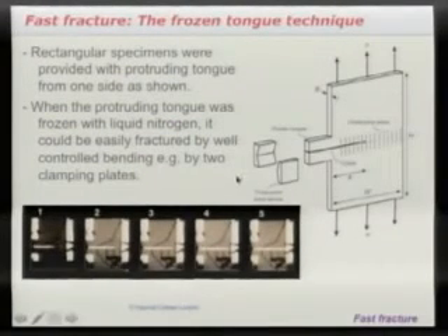And we developed a technique which we're going to demonstrate in a moment, which we coined the frozen tongue technique. And what we did was to take a small section of material, about this wide, load it uniaxially in an Instron testing machine, an old one in those days, but it was still an Instron, and we cooled a tongue section on the left there. And we cooled this with liquid nitrogen.